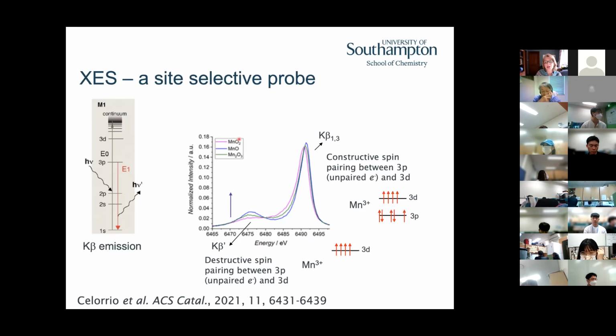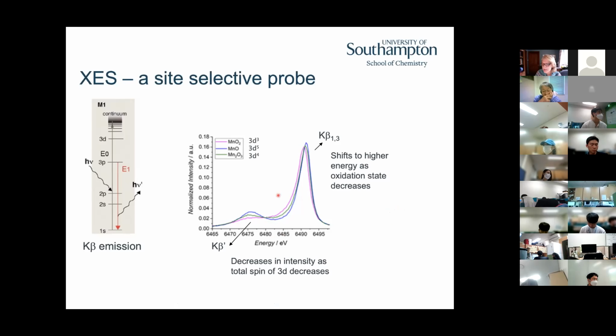And as we change, these are our reference compounds, you can see that we've got two peaks here. So we've got the K beta 1,3, which is the constructive spin pairing between these, gives us this enhanced peak here. And the destructive spin pairing gives us the enhanced peak there. And I encourage you to look at the paper for the details. But in terms of electrochemistry, what this is telling us is this peak shifts to higher energy as the oxidation state decreases. And this one is losing intensity, right, as the total spin of the 3d decreases. So again, that's the occupancy of that d orbital.